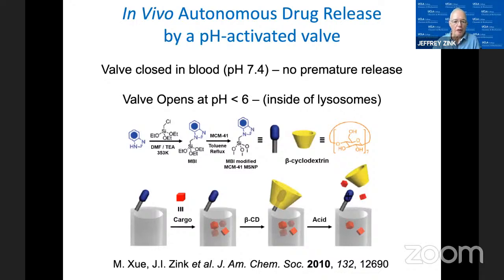So that's an example of a nanovalve. Here's the one that has been most useful biologically. This very simple valve consists of a benzimidazole molecule with a beta cyclodextrin cap. So there's a cyclic cap and the stalk. Those are attached to the surfaces of the nanoparticles, including around the pore entrances. When the benzimidazole is in the neutral form, as drawn here, it's hydrophobic. The hydrophobic interior of the cyclodextrin joins to it by supramolecular van der Waals forces and so on, hydrophobic forces, and the system is stable.